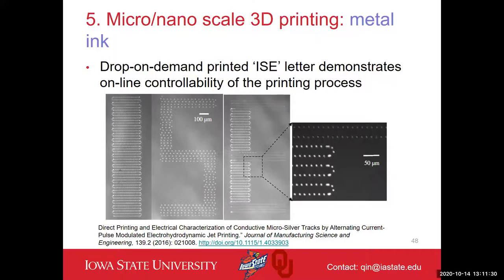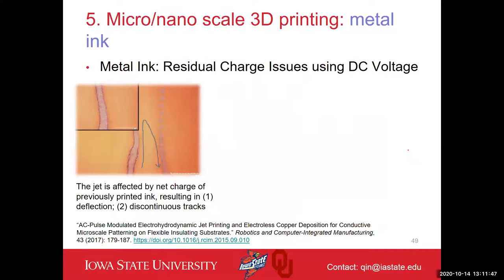Of course, there will be articles from our group that you can follow to learn more about this technique. For the printing, there is voltage applied. For the voltage itself, there are a lot of things that we can control. We can use a DC voltage and we can also use an AC voltage. For DC voltage, there will be a few challenges. For instance, if the substrate is not conductive, the DC voltage printing will generate a charge accumulation, which will affect